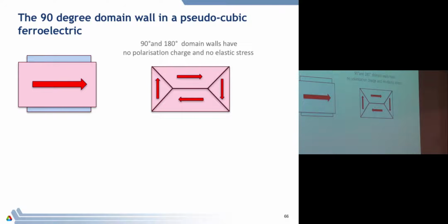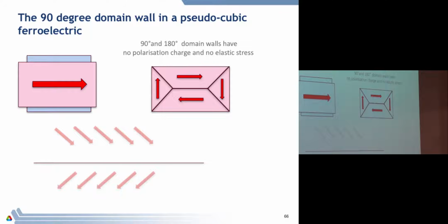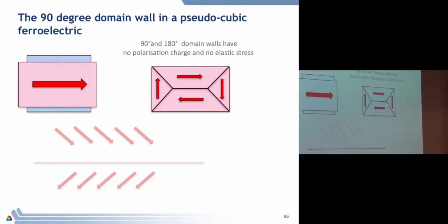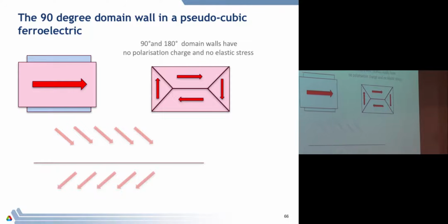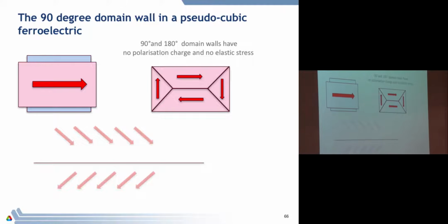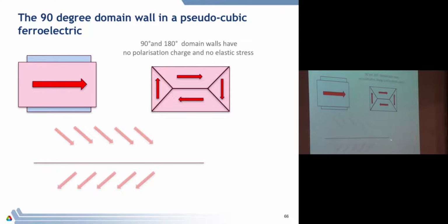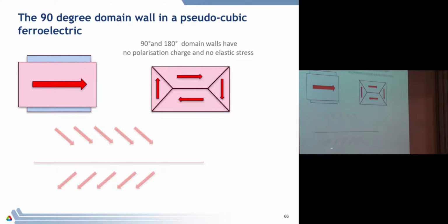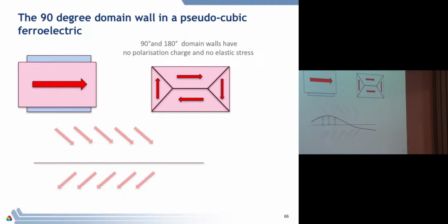Now, by the way, if you're making a ferroelectric device where you want to have lots of little domains and you want to switch them, that's one of the things that you actually have to overcome to make sure that that works. Okay. But now, if I now think about this, if I look at, say, this domain wall, I'd like to know how mobile is this domain wall. So let me extract it from here, draw it along here, and here's the polarization coming in and coming out and like that. And so as a